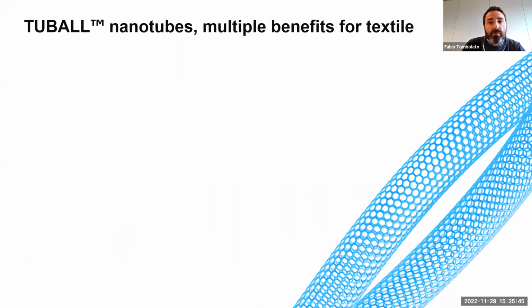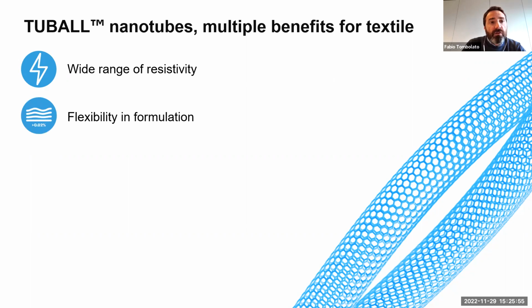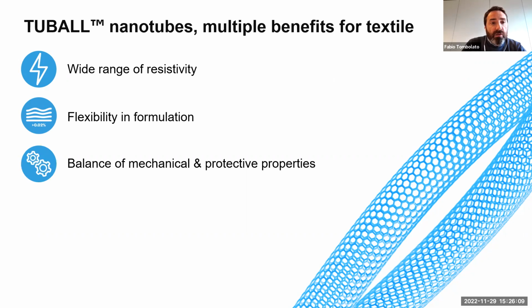TUBALL nanotubes can bring multiple benefits for textile. A wide range of resistivity is possible to achieve thanks to the high efficiency of this material. The very low working dosage, we are seeing that starting from 0.02% of graphene inside the system is enough to achieve the final properties, gives the customer high flexibility in terms of the formulation. The very low working dosage is fundamental to maintain, or even enhance, all the other properties of the material that are important too, like mechanical properties and chemical resistance.